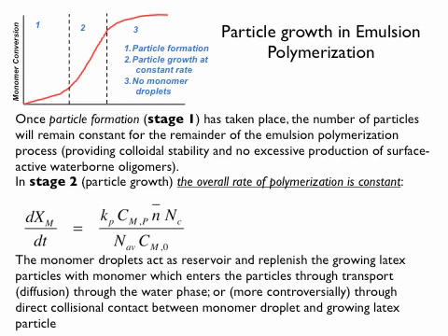Then we divide by the Avogadro number to get it back to molar. In this case, we also divide by the analytical concentration of monomer we put into the system. The only reason that's there is because on the left-hand side we use conversion, so then the equation matches.